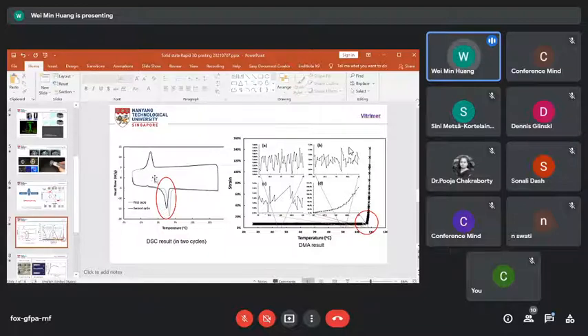And if you refer back to the DSC result over here, 90 degrees, somewhere here, is well above its melting temperature. Well above its melting temperature. The material is melted, but still in the solid state, just like semi-crystalline polymers.